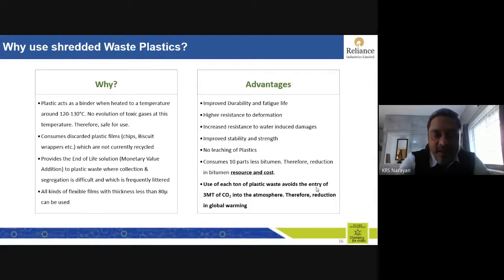The Marshall stability is higher. No leaching of plastics. 10% of bitumen can be reduced. That's dependent on the mix design, so I would not advocate that at the moment. It depends on the mix design. And each ton of plastic waste avoids the entry of 3,000 kgs, that is 3 metric tons of carbon dioxide into the atmosphere. So there is a reduction in global warming as well as a reduction in the carbon emissions. So these are the advantages, how and why we should use shredded waste plastic.